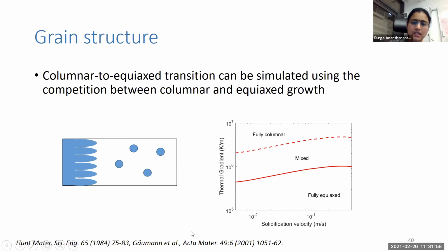Using the Hunt and Gäumann model, whether we finally have columnar grains or equiaxed grains depends on the thermal gradient and the interface velocity, the solidification velocity. If we have very high gradients in this solidification velocity range, then we probably have fully columnar grains. We have to go to lower gradients and higher velocities if we want fully equiaxed grains, so this may not be achievable in many alloying cases. One way to induce more equiaxed growth would be to introduce inoculant particles that act as heterogeneous nucleating sites, and then you'll have grains forming here.